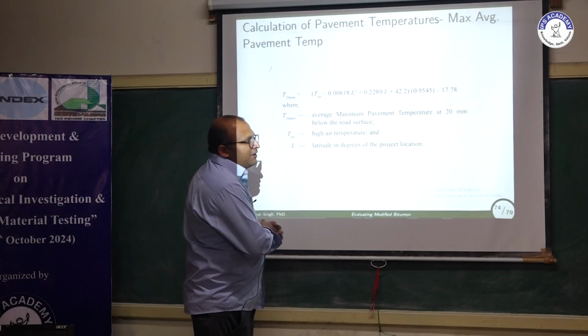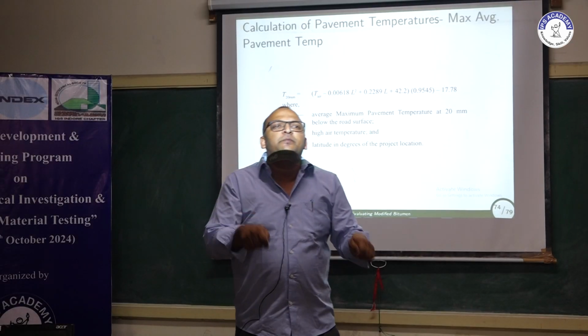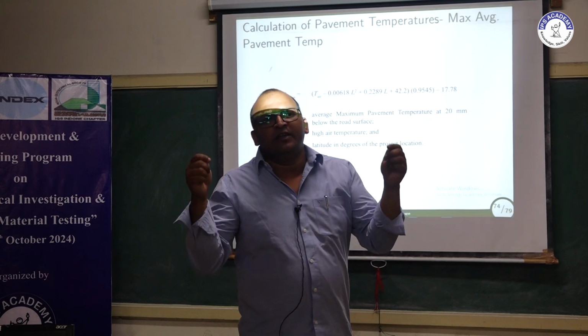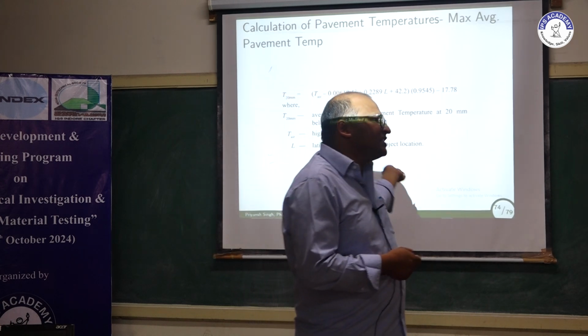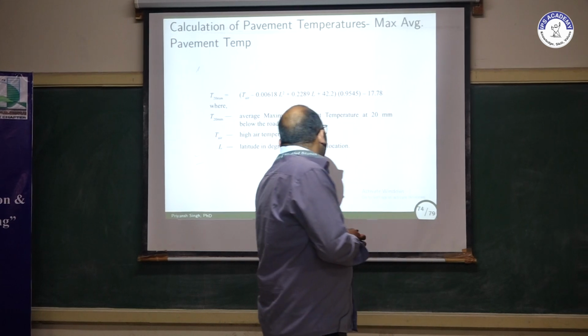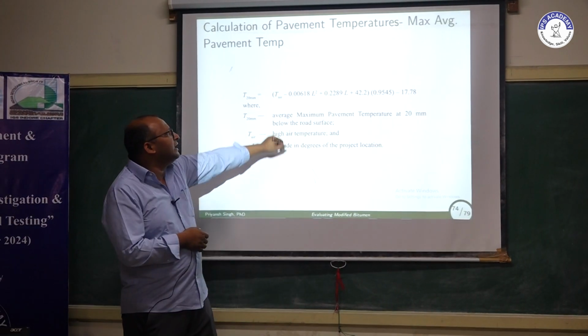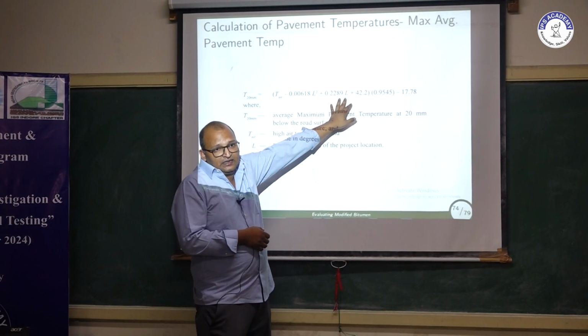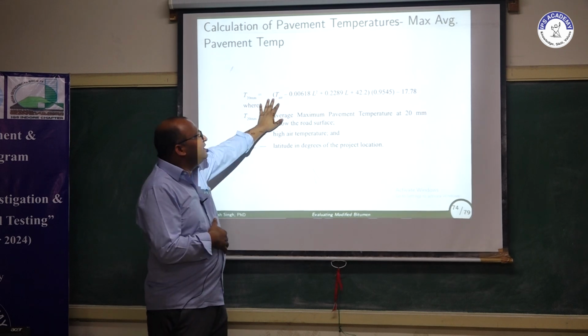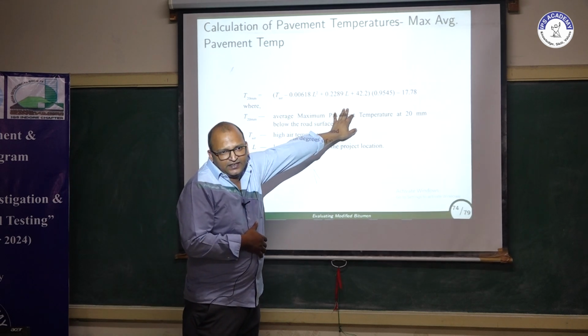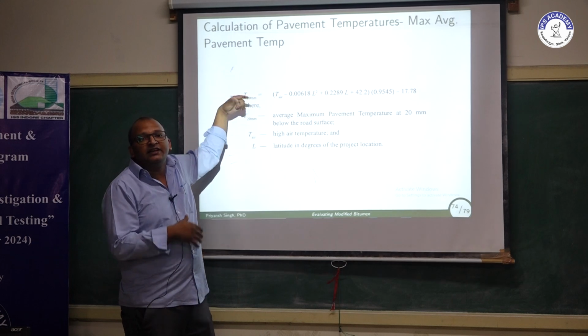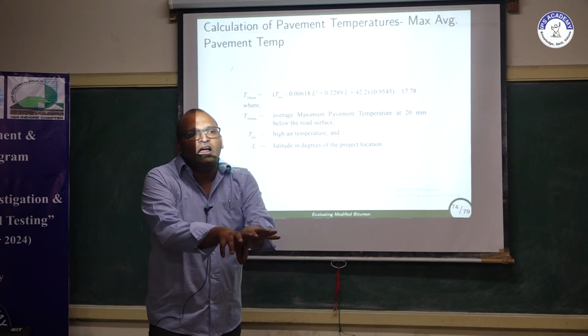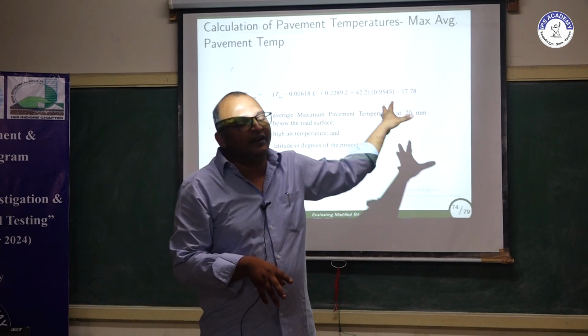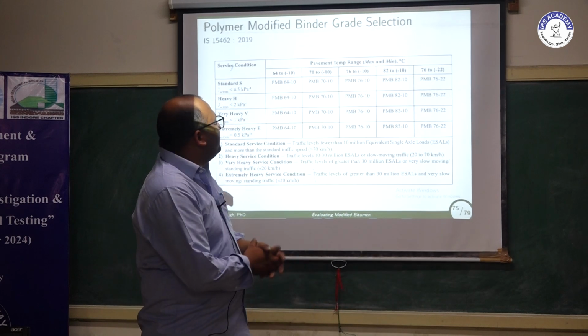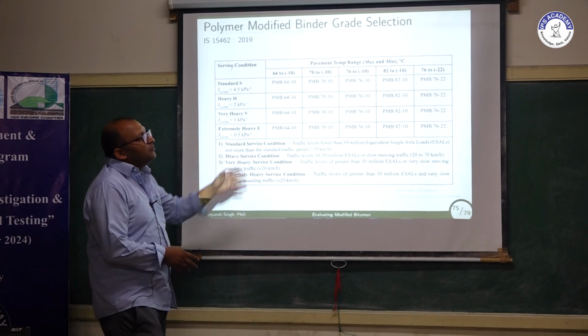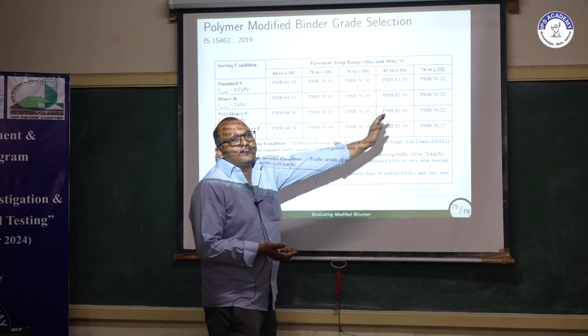Now how to determine the pavement temperature, because you cannot directly measure the pavement temperature. So for that, an empirical equation is suggested by the IS code. That empirical equation is based on the air temperature and latitude of the region. So if you have the air temperature and latitude of that region, you can estimate the temperature at 20 mm depth of the pavement. That will be the input of your grading. So based on all this information, we have these grades of binder which you have already seen, the 5 different grades.